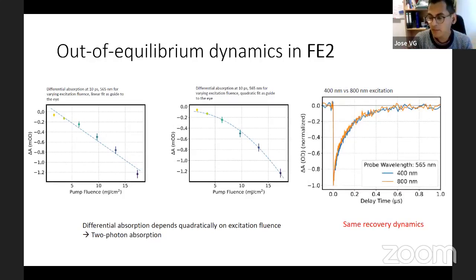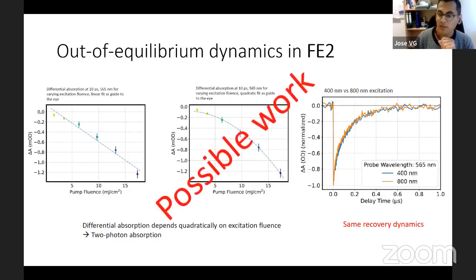What about the recovery? Well, we observe more or less that the recovery after excitation at 400 and 800 nanometers is the same. So when we excite in the crystallographic experiment at 390 and 780, we expect also the same recovery from high spin to low spin. And this is still work in progress. While the iron 4 and iron 3 are projects that are complete, this 2-photon absorption in the iron 2 is still missing. There is some information I'm still working on. And if a student comes and I haven't finished, this will be a possible work for this coming student.